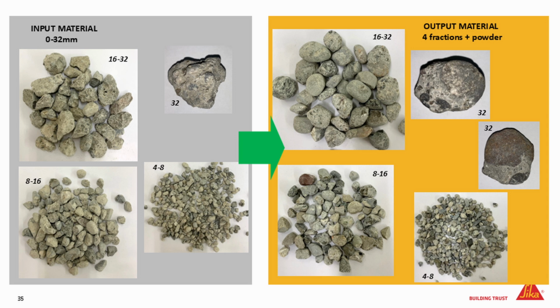That means that we do not want to crush the aggregates, because when you crush them, you get rough surfaces which require a higher water demand. So we want to keep the surface area as low as possible. That also can mean that we still have some agglomerates, and you see it here, that we still have some cement stone in between the aggregates, but you see clearly the cleaning effect.